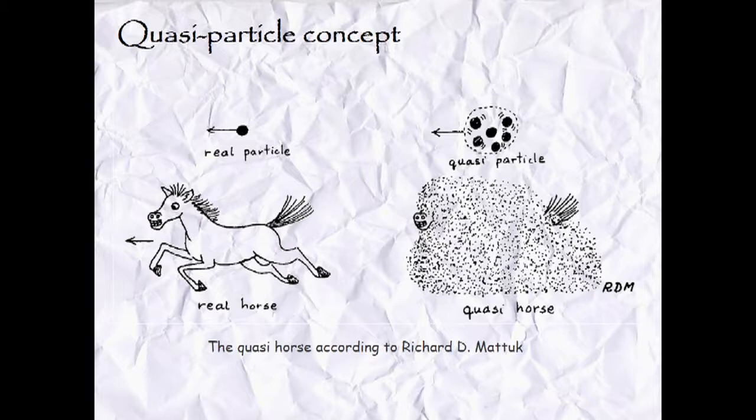Could be electron-electron interaction, but you also could treat the same thing, electron-phonon interaction, electron-magnon interaction, whatever you think of. So all the interactions an electron is exposed to can be cast into a new kind of particle that we call a quasi-particle. And the interaction between the quasi-particles is now very small and negligible, such that we can interpret these quasi-particles with its